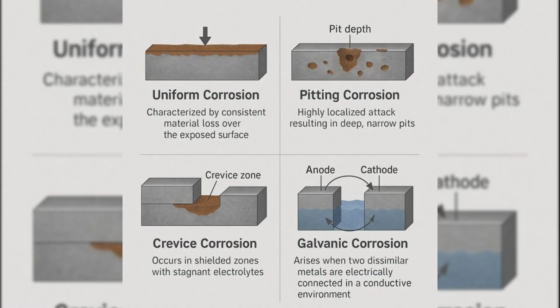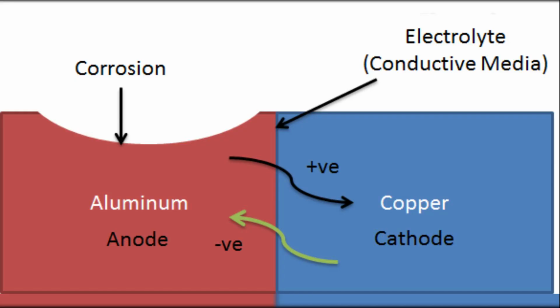Another major threat is galvanic corrosion. This occurs when two different metals are electrically connected and exposed to an electrolyte. Together, they form a galvanic cell. The less noble metal becomes the anode and corrodes much faster than it would on its own. The more noble metal is protected at the expense of the other. Poor material selection, such as directly joining steel and aluminum without insulation, can turn an otherwise solid design into a corrosion failure waiting to happen.